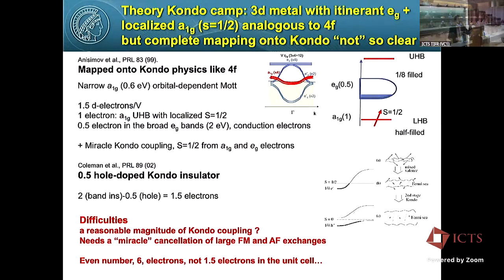Of course, if you take a look at susceptibility at high temperature, I do see Curie-Weiss behavior, and neutron inelastic scattering does see some strong spin fluctuation. So in that sense, it's there. But my point is, the difficulty is that everybody criticizes this picture because, having a Kondo coupling, they need a miraculous cancellation, and many people didn't believe it.